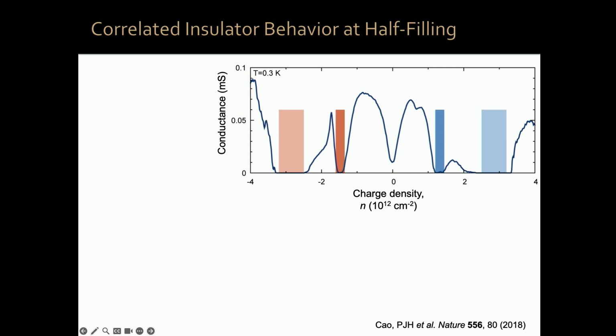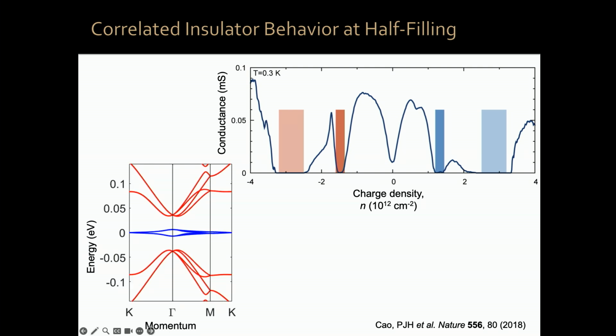This is the electronic structure of magic angle twisted bilayer graphene. I showed it to you earlier. It turns out in these flat bands, okay, if you start from zero, to get to the top of the band, you have to add 4 electrons per moiré unit cell to the system. Remember I told you to remember 4? Yeah? If you want to empty this band from zero, you have to remove 4 electrons per moiré unit cell. So you have in total actually 8 electrons per moiré unit cell that can fit in these flat bands.